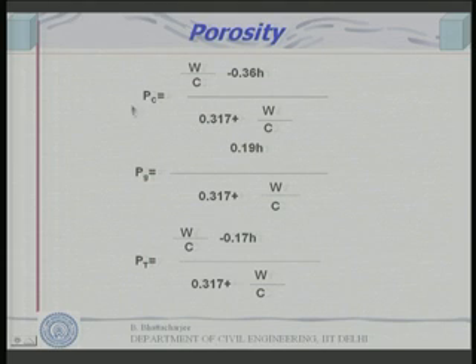W by C, you can derive this very easily, it is not a difficult task, because the original volume is known, the volume of the solid gel is known, the volume of the gel pores is known, and the volume of unhydrated cement is known for a given degree of hydration. So we can find out the rest of the volume: the original volume minus the volume of gel pores, gel solid and unhydrated cement will give me the volume of capillary pores. So I can find out the capillary porosity.